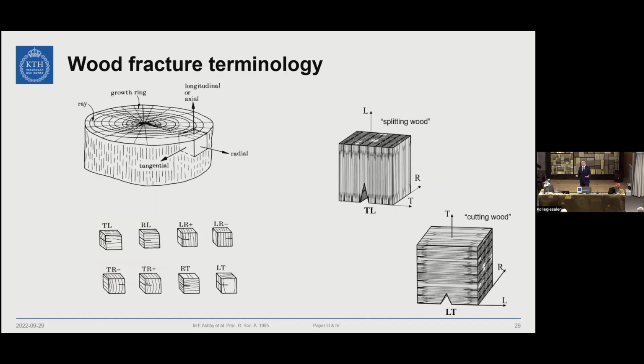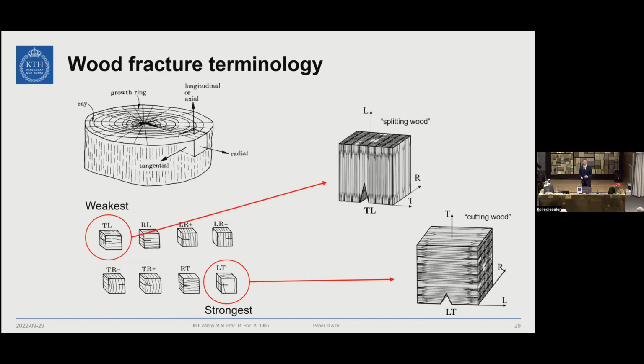For the sake of this presentation, I want to establish the fracture terminology. So wood, as I said, is an anisotropic material. There's a complex way a crack can propagate through wood. There are 8 different ways it can propagate. But we will focus here on the weakest one, which is called TL. So the crack is propagating along the fibers, but loaded in the transverse direction. And then the strongest, where the crack is trying to propagate through the fibers.